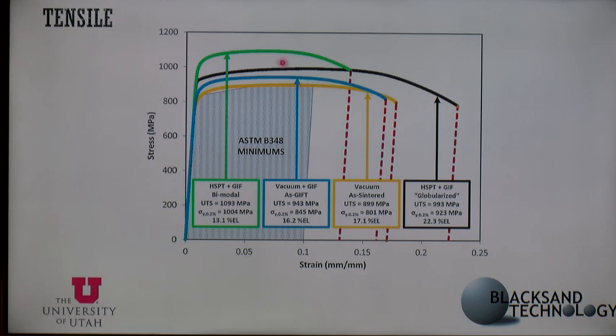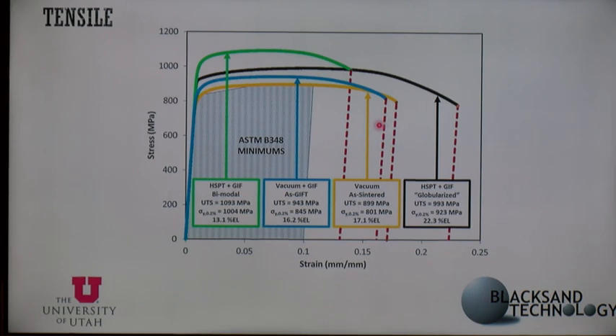As you can see with ours, they not only exceed the ASTM standards, but they also exceed vacuum sintering by quite a bit. Especially they see an increase past what's called the strain, so how ductile the material is. So we not only have stronger but more ductile materials than previously were invented. If you think about it like this, we can have a material that's cheaper to produce but also stronger than what was previously able to be produced.